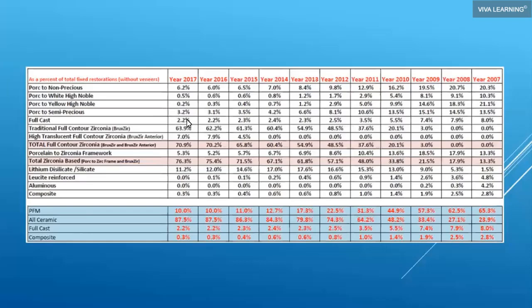But here's where the number gets crazy. If we look to 2007 and we look at the amount of zirconia done in the lab, almost zero. Back to 2009, almost zero. Fast forward 2017, we look at zirconia, 70% of the crowns were zirconia. But now if we keep going down the line and we look at lithium disilicate, that accounts for another 11% or 12% of the space.